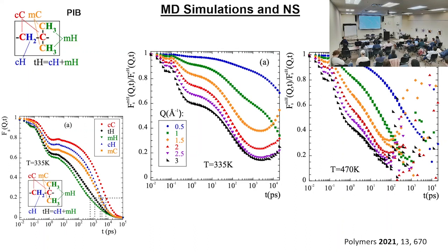Now when you do this, you are looking at the rotational part only. Rotational part is a confined motion, so at long times it should be compatible with EISF. That means there should be a plateau. So you see some plateau at higher Q values, but nothing on the lower Q side. So by doing this and looking at EISF, they were able to conclude that in this particular case, statistical independence does not work.